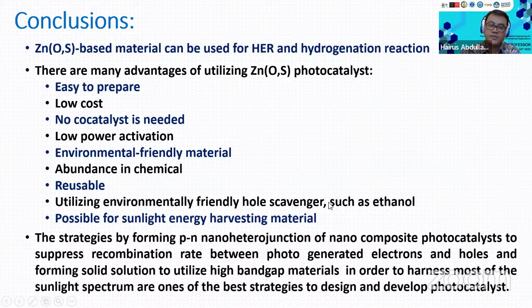We have seen that many toxic reagents are used during the hydrogen evolution reaction in other works. But in this case, we only use ethanol, which is very friendly to the environment, and it is also possible to use sunlight energy harvesting. The next one is the strategy of forming the PN junction, which is also very promising. We see that it suppresses the recombination rate and improves the charge transfer. That's why the efficiency is enhanced.